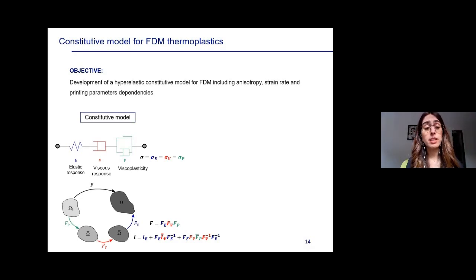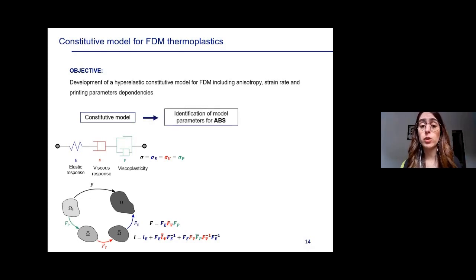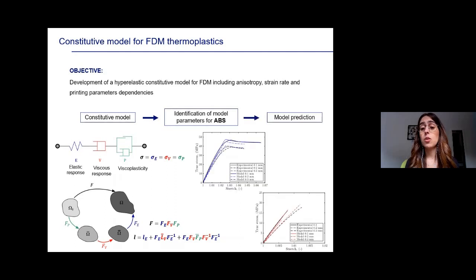And I would like also to say that to do that, we went from the reference to the current configuration using two extra intermediate configurations. Once we have the formulation, we identify the model parameters for a specific material, that is ABS, one of the most used in 3D printing, especially for fused deposition modeling. And finally, we validate this model by comparing the predictions with the experimental results.